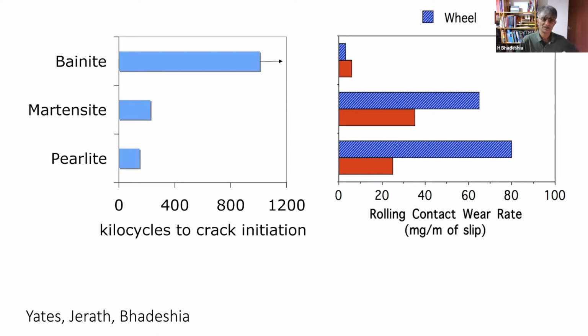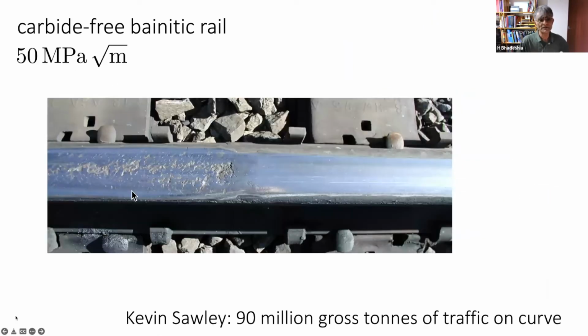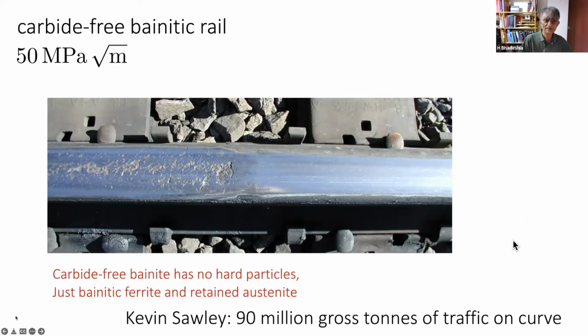A rail is a safety-critical application. You can't simply say, we've got these data, we're going to put them into service. But in the US, there is a test track, where heavy traffic just goes round and round, and the rail was installed there. This is ordinary rail, and this is the new rail, and you can see the level of damage here compared with here after 90 million gross tons of traffic. And the reason for this performance is that the structure we have created doesn't have these hard cementite which ordinary perlite has. In fact, the surface hardens even more because the austenite transforms by this deformation of the rail.